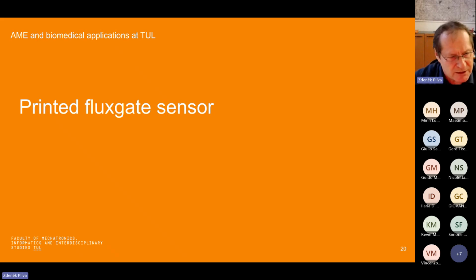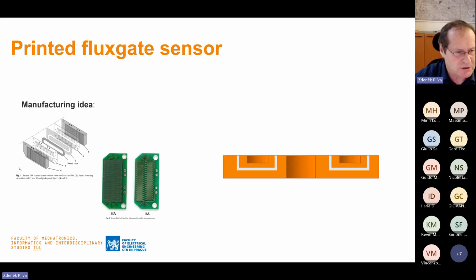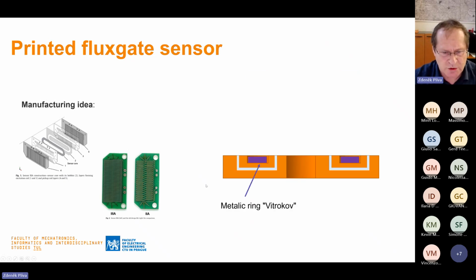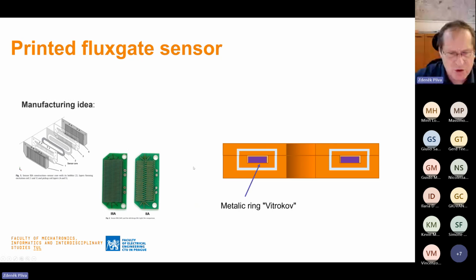Yeah, so the final part of my presentation is focused not on medical application, but I think it's also interesting. That means the printed fluxgate sensor. The main idea was to replace the standard PCB manufacturing technology based on FR4 material with a printed version. So our idea was to print some cavity in the sensor, then put a metallic ring inside this cavity. It was made by Vitrokov. Then fill the gap between the printed material and the core of the coil, and then continue with the printing process to close the windings around the core of the coil.